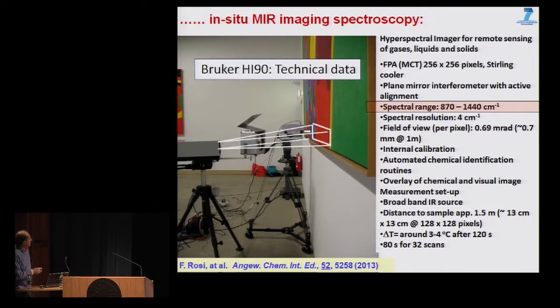In this case, a lamp in the infrared is needed. You can see this is portable, it's heavy, about 30 kilograms, but it can be put on a tripod just in front of the painting at a distance of about 1 meter. The inconvenience, if it is an inconvenience, is that the spectral range is quite reduced, from 870 up to 1440 cm-1. But we are in the mid-range where it is possible to find some significant bands.